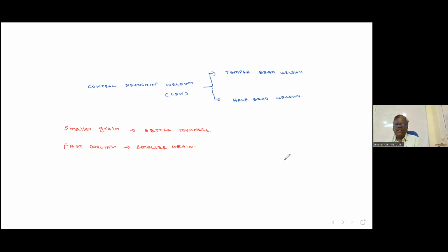Now suppose I have made a weld. For example, this is my weld edge preparation. The first pass we call the root pass. The second pass is called the hot pass. When you are welding a hot pass, understand this please, the root pass is also heated to more than 900 degrees centigrade. 900 degrees centigrade is the approximate upper critical temperature of steel. So when you are welding a hot pass, the root will partially fuse and the remainder will also be heated above 900. When you move the hot pass fast, the root pass also will cool fast and the grain size will become small. The same way, for any pass you are welding, you can alter the grain size of the previous pass.